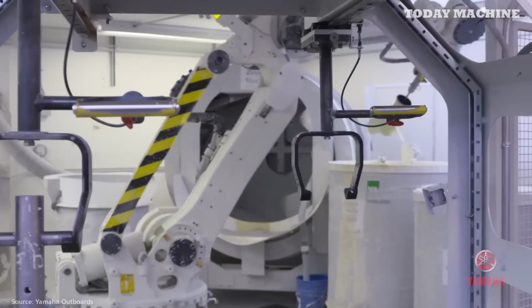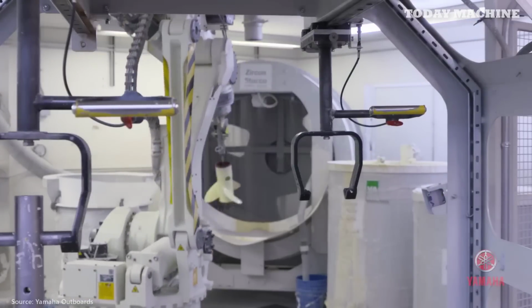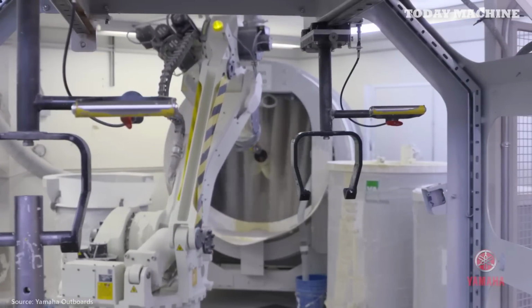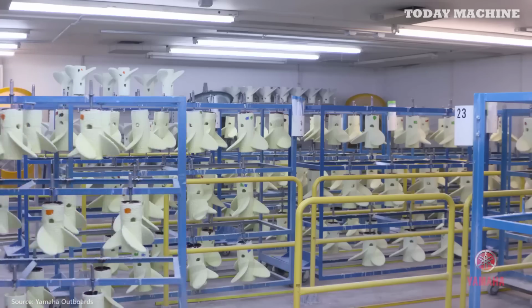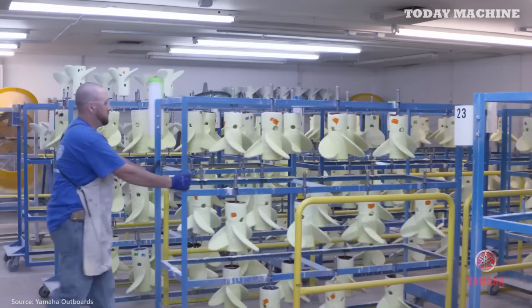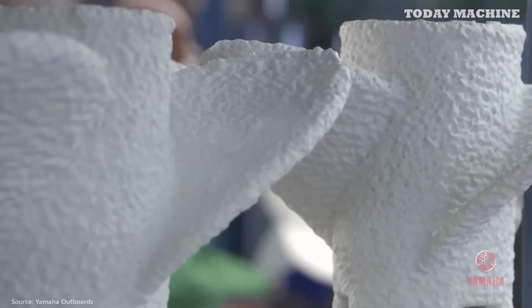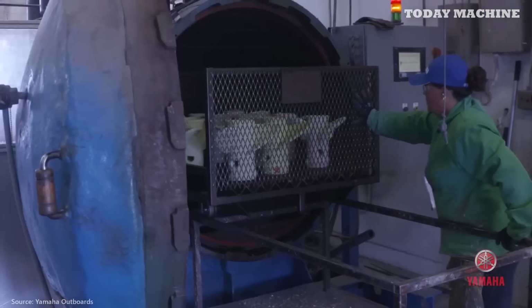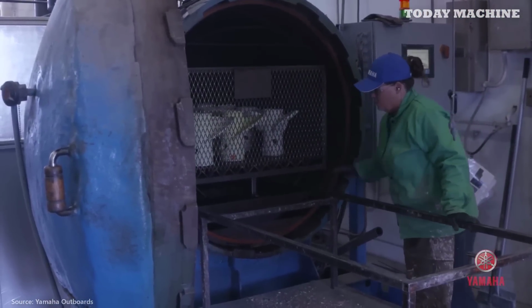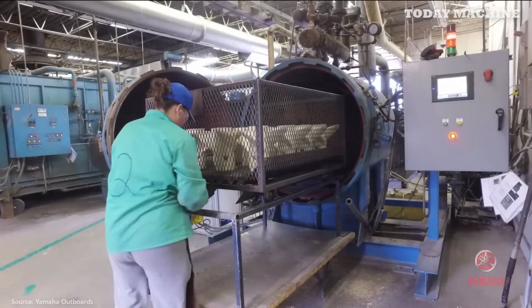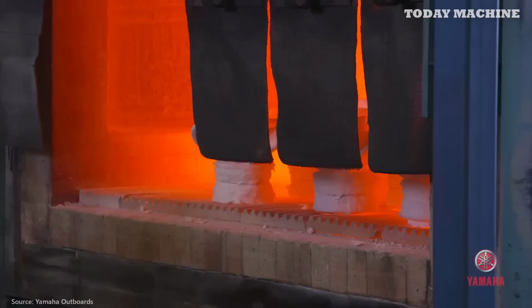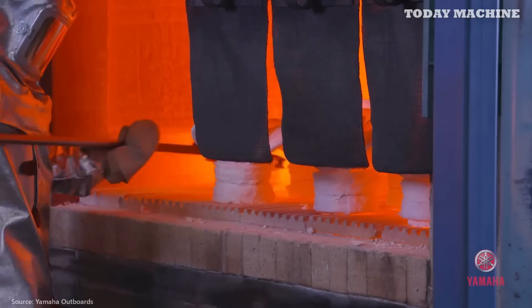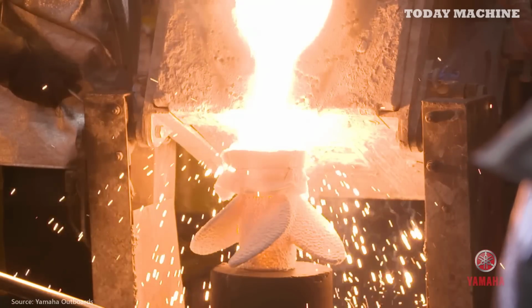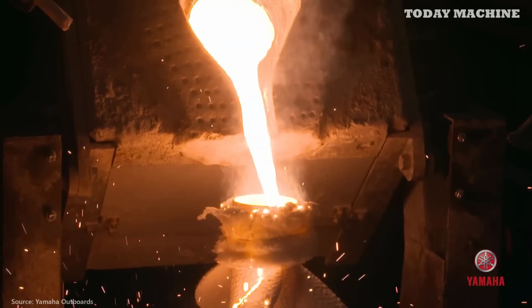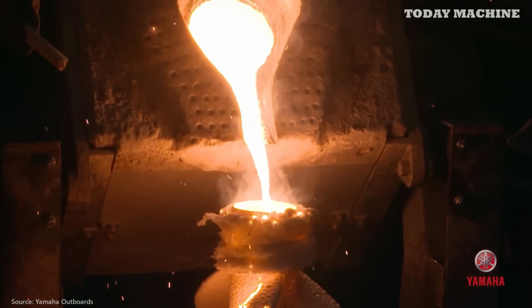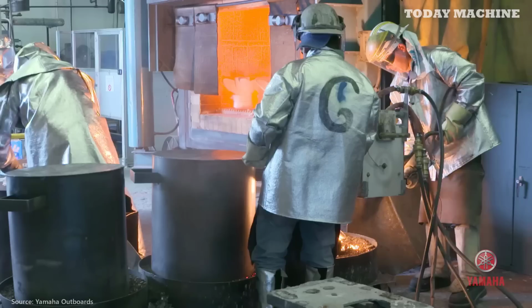The wax is removed by melting it out in an autoclave, with the recovered wax recycled for future use. The ceramic shell is then baked at 1,800 degrees Fahrenheit to strengthen it further. Molten stainless steel, heated to approximately 3,000 degrees Fahrenheit, is poured into the prepared mold. For propellers, a 15:5 stainless steel alloy is used, comprising 15% chromium and 5% nickel for strength and corrosion resistance.